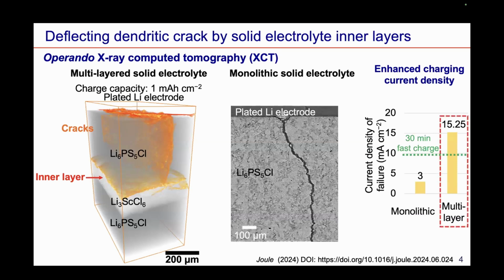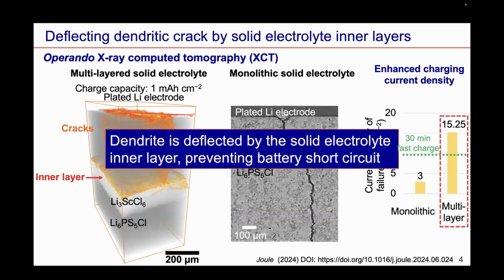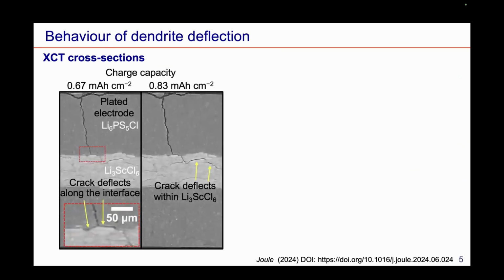So this result indicates that the dendritic crack or the dendrite growth can be stopped by introducing such an electrolyte inner layer. And this will prevent the battery short circuit even under a very high current density. Now let's focus on the behavior of this dendrite deflection. These are the XCT cross-sections of two selected charging states.